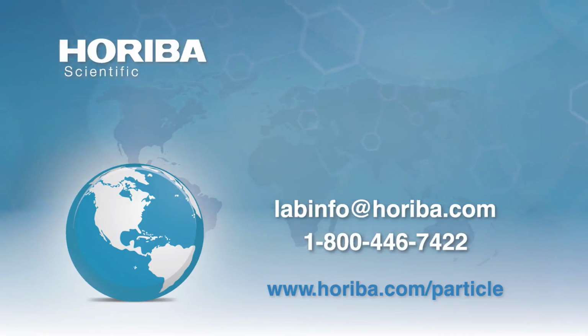If, let's say, the droplets are small enough, the droplets might be okay, but you might have very fine crystals in there where you want to use Mie scattering, and basically you have to convince yourself that you've figured out one piece of it. Say you've got this bimodal distribution, and you've got a piece of it figured out, what the size is, and now you might end up having to recalculate the PSD based on a different refractive index for the other phase.